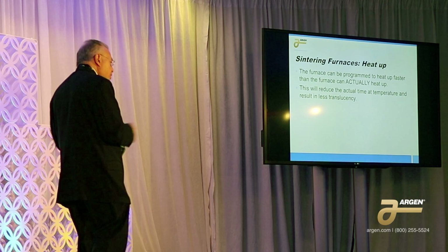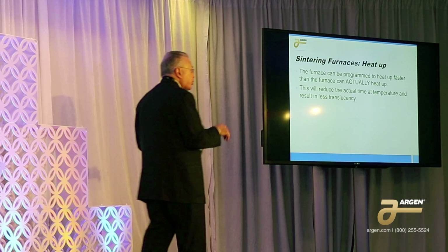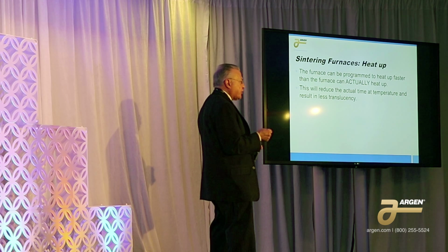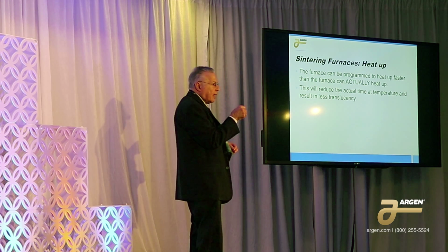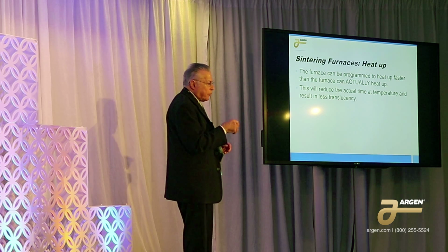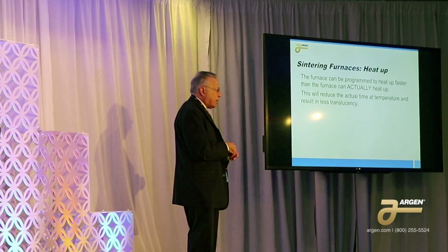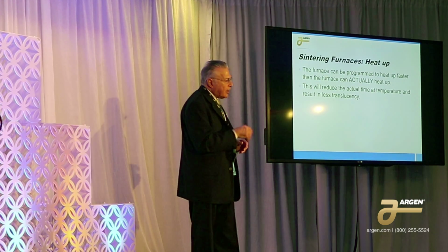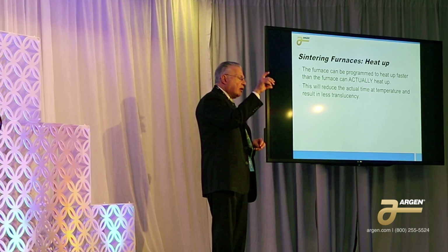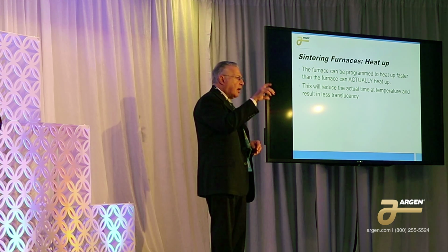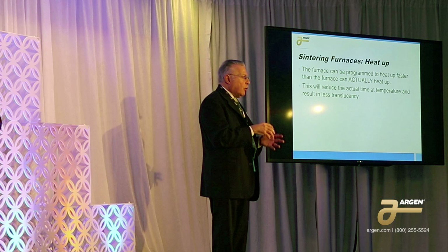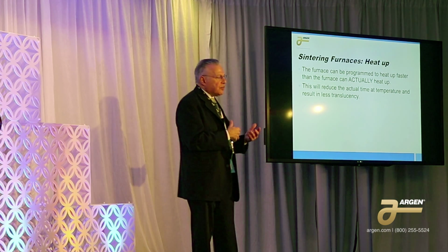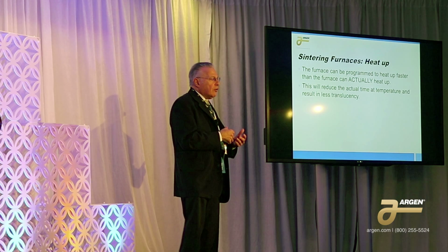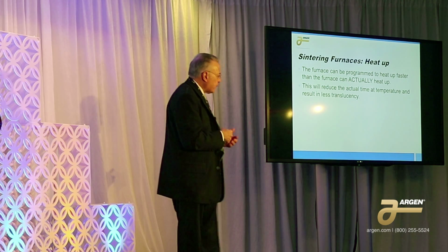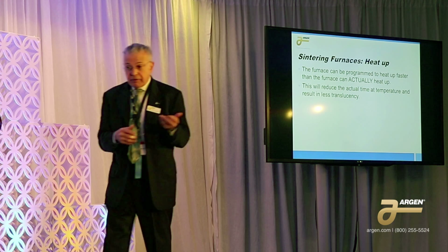Also, you have to remember, because the furnace has a certain amount of thermal mass, you could program the furnace to go faster than the furnace actually can. So that little electronic thing that says 99 degrees a minute, well, you could put anything you want on the number, but that doesn't mean the furnace is going to follow it. And what that could mean is that you're actually cheating the material on the top temperature, so your hold time actually gets shrunk. So on heating, we'd rather see something like 10 degrees a minute rather than 30 degrees a minute. And on cooling, it's even more important to go a little slower, especially down to 950.